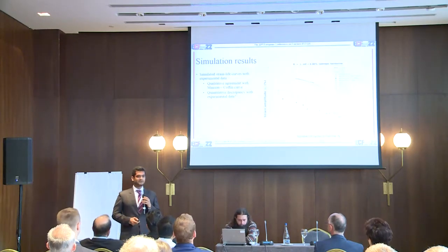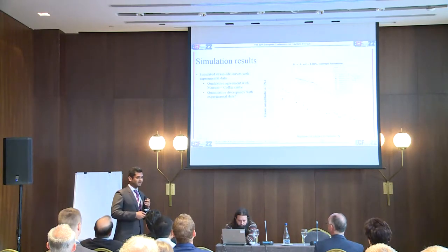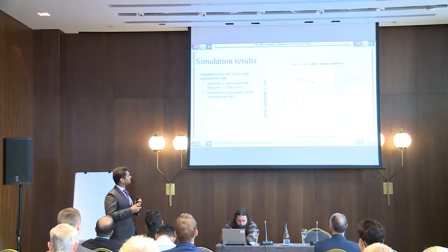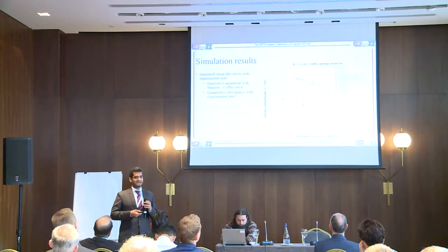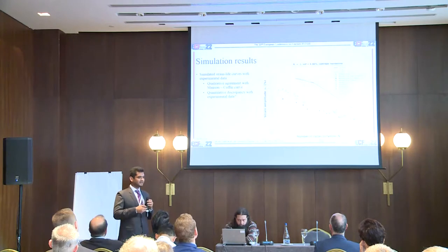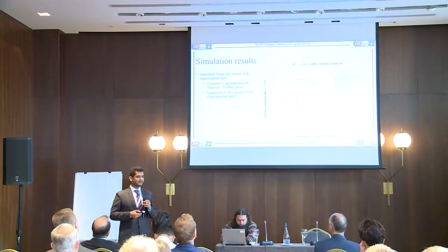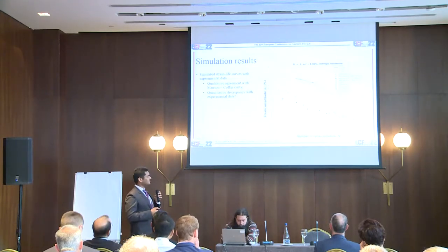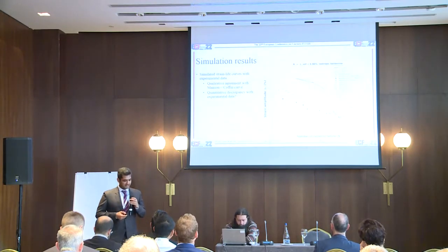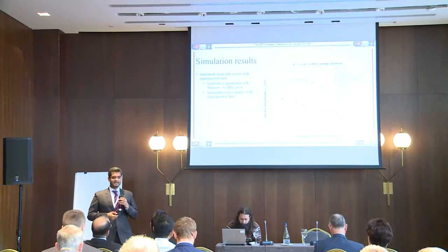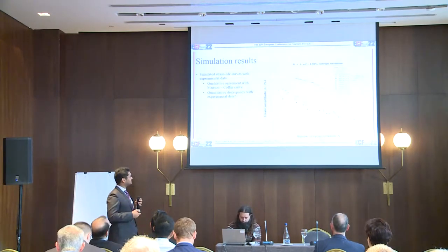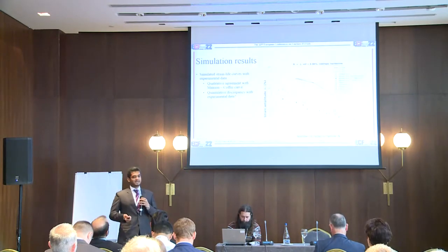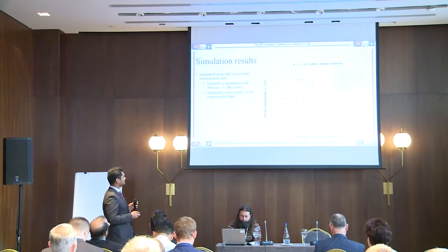Now, having developed the methodology and simulation model, we applied different strain amplitudes and extracted the number of cycles to failure. We also studied the effects of different types of matrix hardening: when n equals zero, the matrix is elastic ideal plastic, and with increasing hardening exponent, we increase the hardening. The conclusion is that with increasing hardening, the number of cycles to failure decreases. This data also shows experimental data collected from literature for the same low-cycle fatigue test. The first observation is that our model and methodology can explain low-cycle fatigue in nodular cast iron qualitatively. However, there is a large quantitative mismatch, likely due to many assumptions made in this initial model, and we decided to investigate these reasons by implementing improvements one by one.